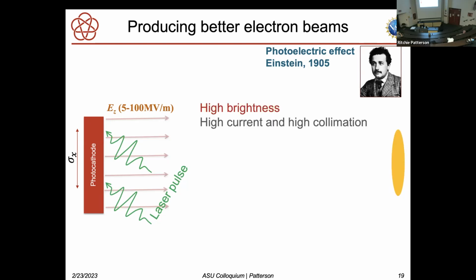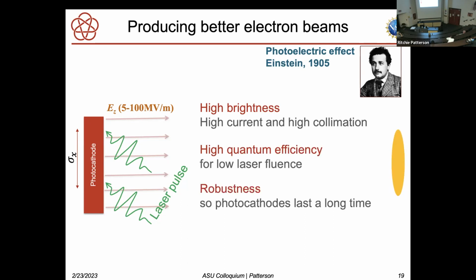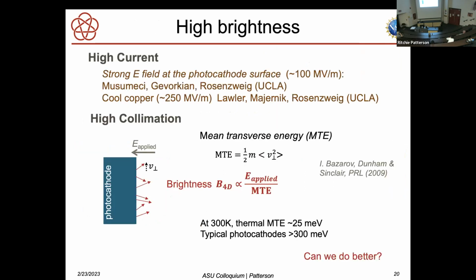So what do we want? We want high brightness. That means we want a lot of current and high collimation. We'd like to do that with high quantum efficiency so that we don't have to blast it with a laser. And we want robustness. We want photocathodes that last a long time because we don't want to be going in and swapping them out all the time. So for high current, you need a strong electric field at the photocathode surface, and we're talking typically about 100 megavolts per meter or more.